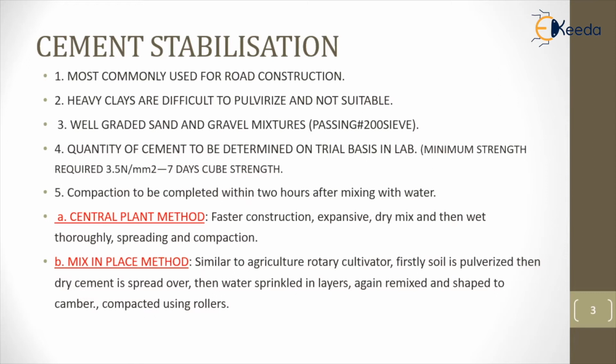Next, the quantity of cement can be determined by a trial and error method in the lab, and the minimum strength required is 3.5 Newton per square millimetre after 7-day cube strength. Next, compaction is to be completed within 2 hours after mixing the mixture with water.